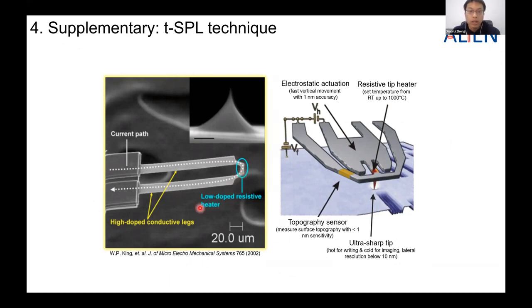We introduce different doping levels of the silicon, and here is a low doped silicon which has a larger resistance. When flowing the current, the heat will be accumulated here and transmitted into the tip. And this type of cantilever is still using a laser diode as the sensor to determine the positions. And this cantilever is developed in NanoFrazor, and they use two resistors.